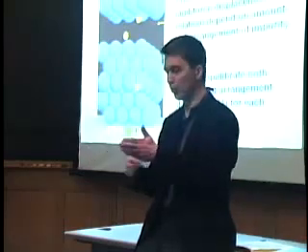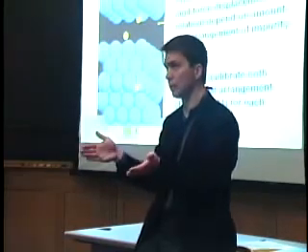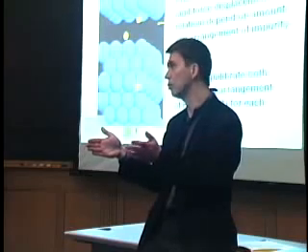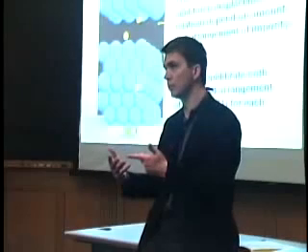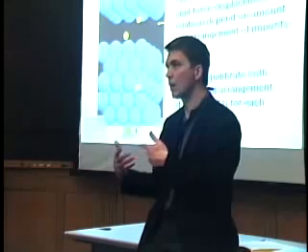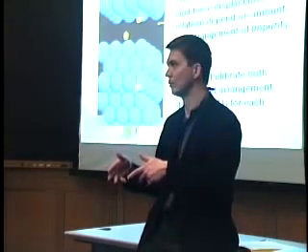So you see the hard problem you have: not only do you have to arrange the impurities in the most stable way, because that's going to determine the energy and therefore the force it requires to open up those planes, but you also need to equilibrate the amount of impurity in that crack. And so this is actually why it's so hard to include chemistry in mechanical calculations, because you're really working on two different time scales that are very hard to combine.